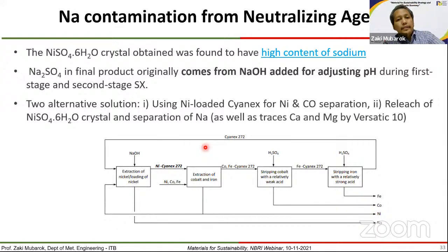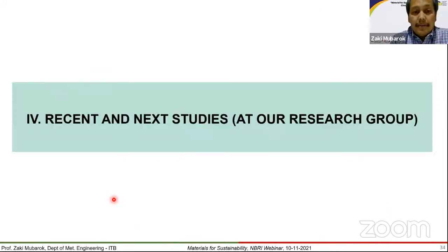The problem we face is the contamination of sodium, which originally comes from pH adjusting agents, during the first stage and second stage SX. Two alternative solutions we have now tried by using nickel-loaded Cyanex. Although we add sodium hydroxide, it will not be extracted in the organic, because the organic already contains nickel. So basically we can separate nickel, iron, cobalt, and sodium, and produce quite pure product.